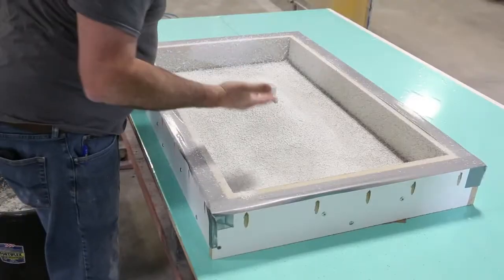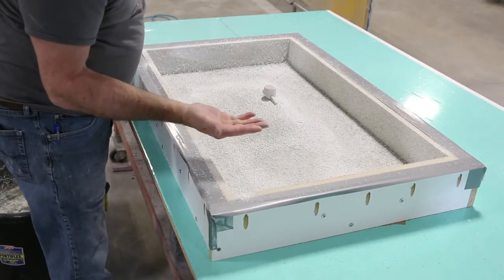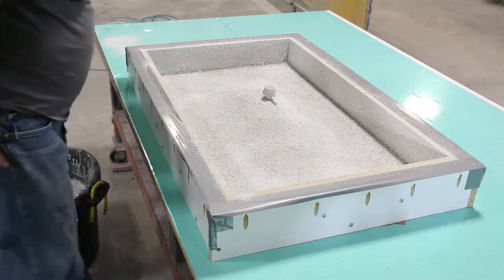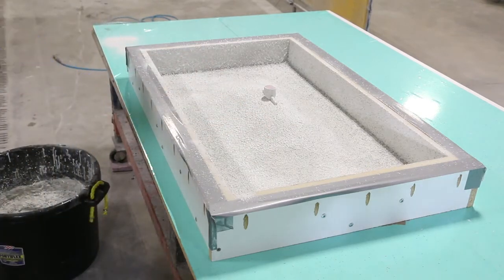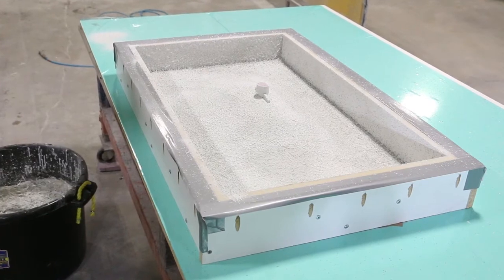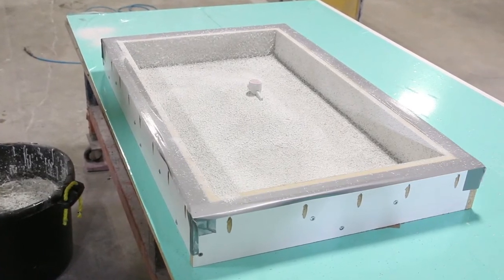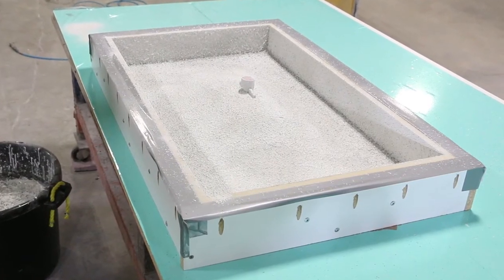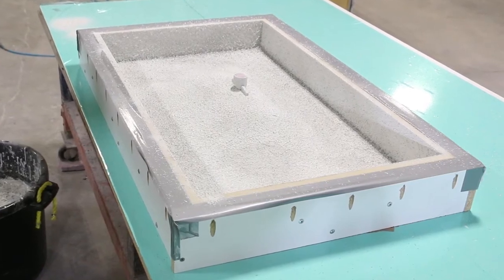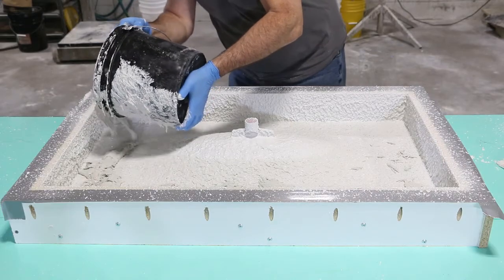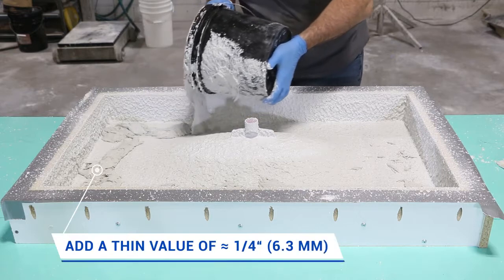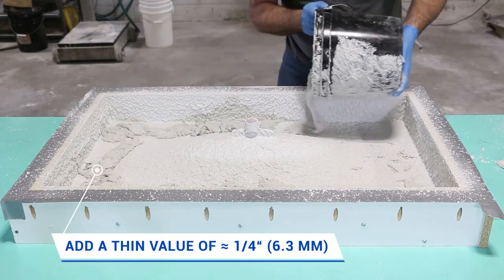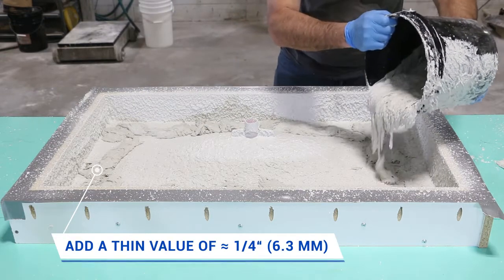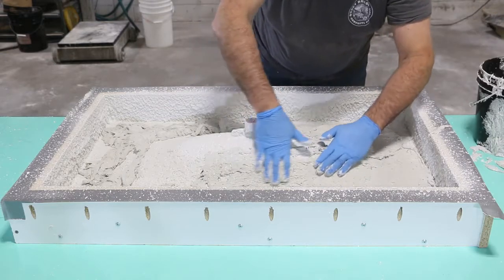Before placing the backer coat, I tested the timing with a light finger pressed onto the face coat, making sure no material is removed. This timing will always depend on ambient conditions, but a visual sign is when the wet sheen or shiny appearance has left and the surface appears dull. Begin by placing a thin layer, approximately 1/4 inch of material onto the face coat, and with light pressure massage the material onto the surface.